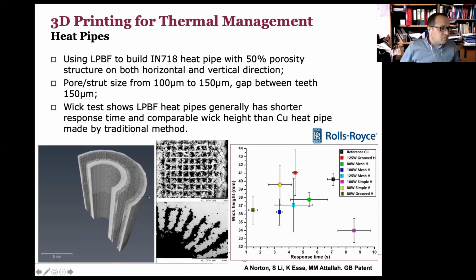They are very rough, but being rough was also very good, because if you compare the response of these structures we printed and how quickly the liquid will climb in terms of the wicking behavior, you can see that the copper reference had a response time of around 7 seconds or so to reach around 40 in terms of the wicking height. Whereas the structures made by additive manufacturing using simple notches or simple grooves or simple shapes that we printed similar to those ones was able to get to roughly the same height but in a much shorter time. So in fact, playing with the topology, playing with the design, we're able to achieve a more efficient cooling and much more rapid thermal response from these shapes and structures.